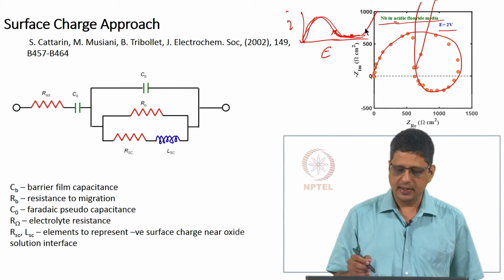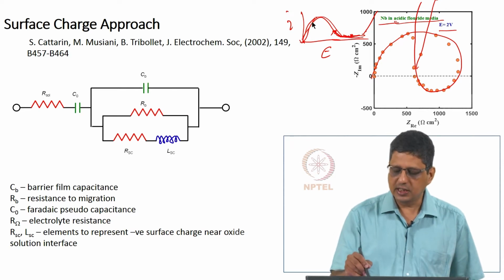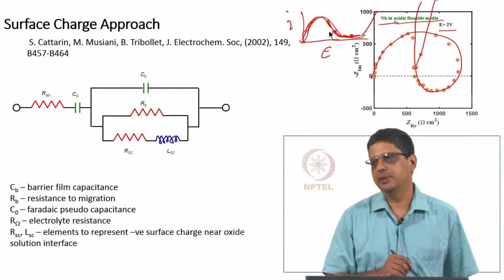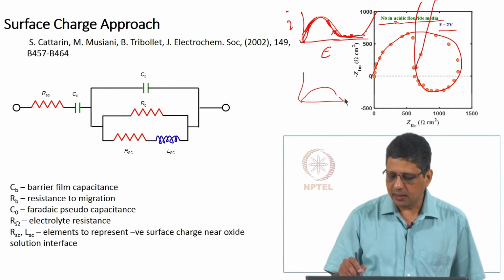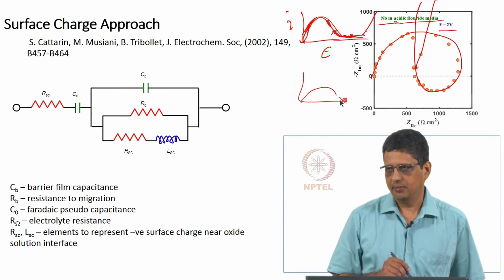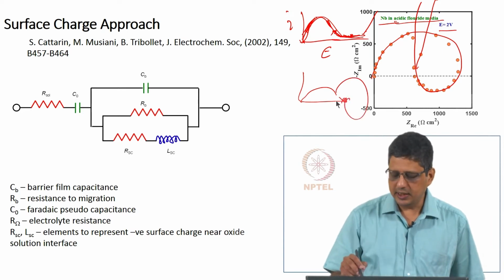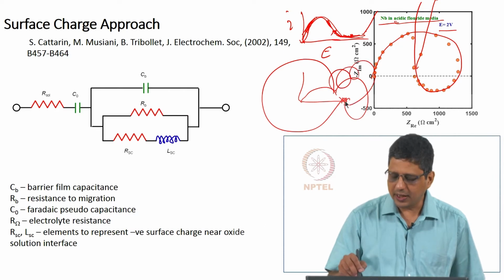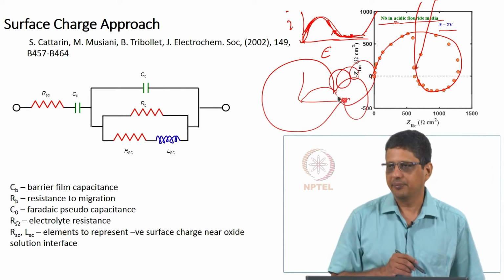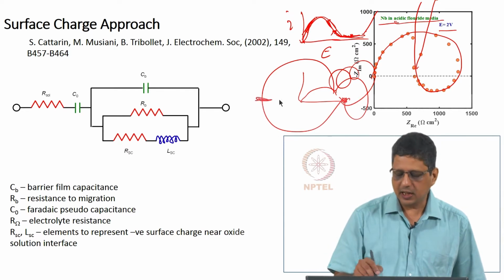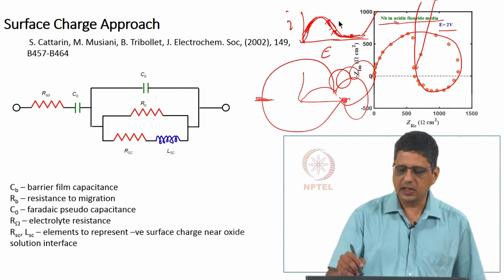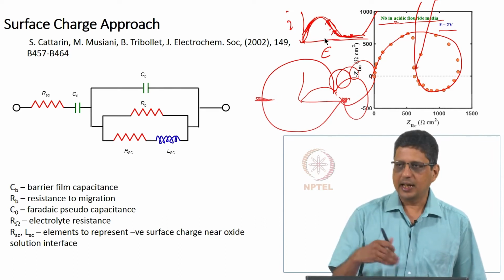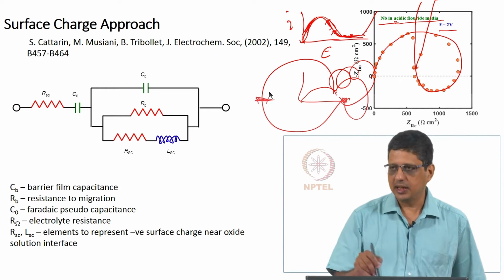Now, we have seen earlier that the slope of this curve gives us the low frequency impedance, correct. Meaning, if this slope is positive, I expect the low frequency impedance to come and end here. It may come and end like this, it may come and end like this, it may do whatever, but it has to end somewhere there. If the slope is negative, it will end at this location, negative side, and of course, I can get it quantitatively also. I look at the slope, that gives me dI by dE, I calculate dE by dI, and with an experimental error it has to settle there.